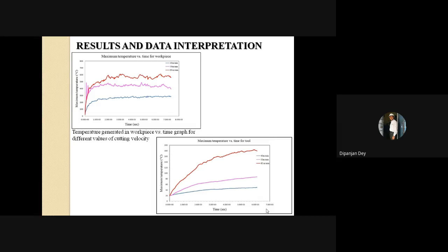These are the graphs for temperature generated in the workpiece versus time, for different values of cutting velocity. We have tried to vary the cutting velocity. This is for the workpiece, and the next graph is for the tool. You can clearly see that as we vary the cutting velocity, the temperature also varies, which is in agreement with the experimental data.